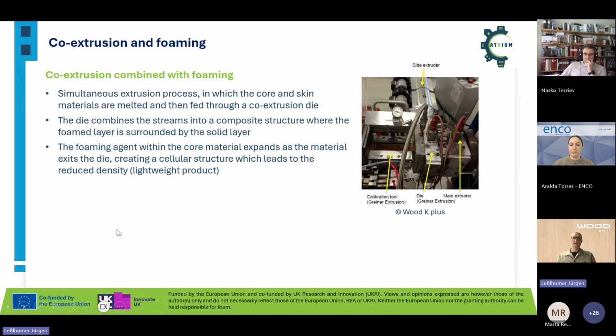And how is this done? We have a simultaneous extrusion process in which the core and the skin materials are melted and then fed through this co-extrusion die. The die combines the streams into a composite structure where the foamed layer is surrounded by the solid layer. And the foaming agent within the core material expands as the material exits the die, creating a cellular structure, which leads to the reduced density and to a lightweight extruded profile.